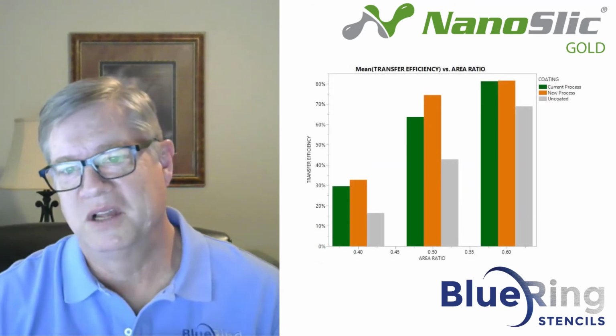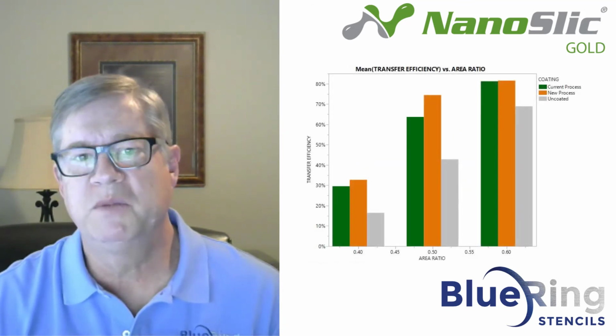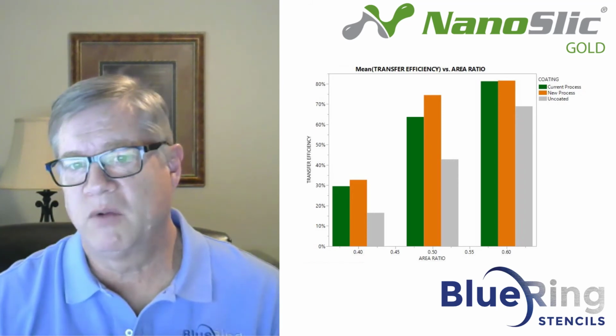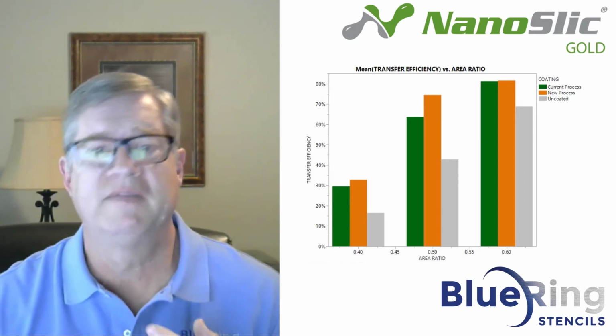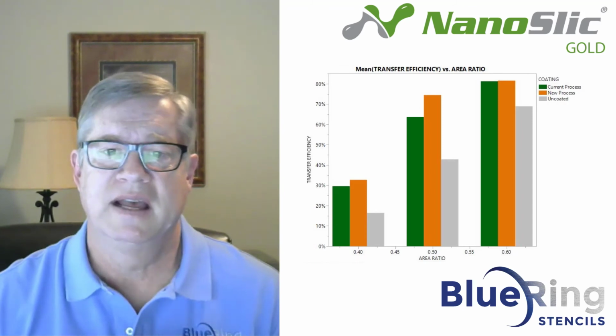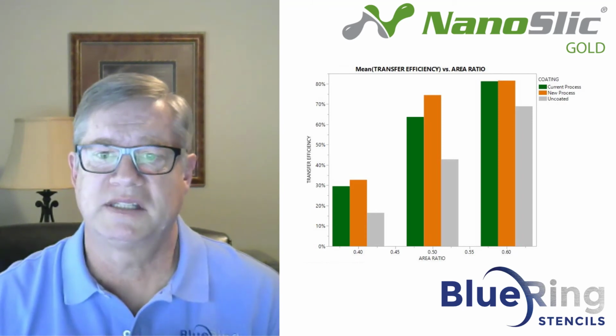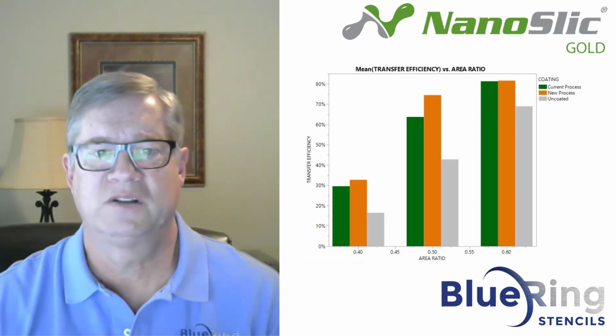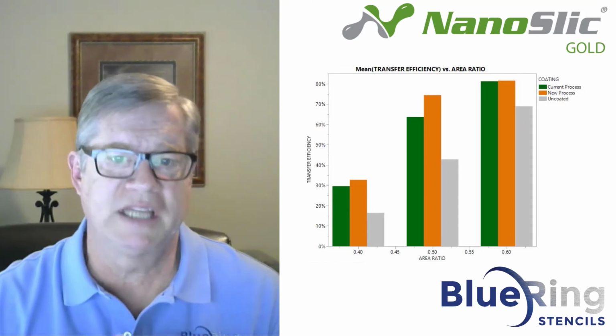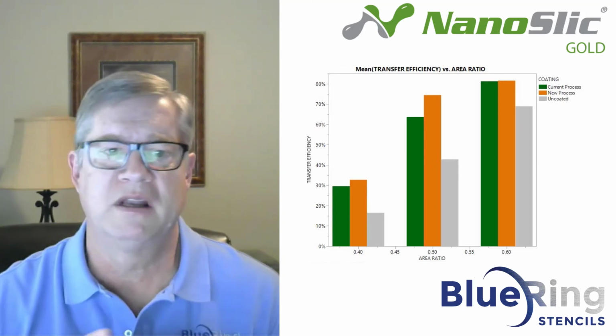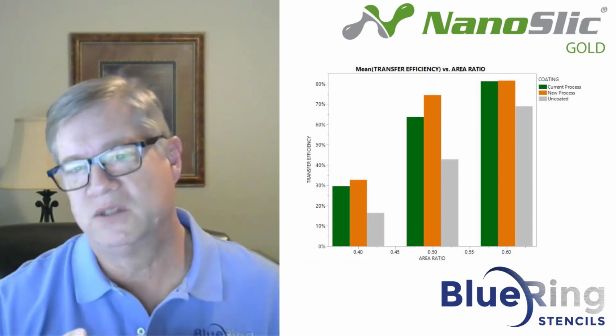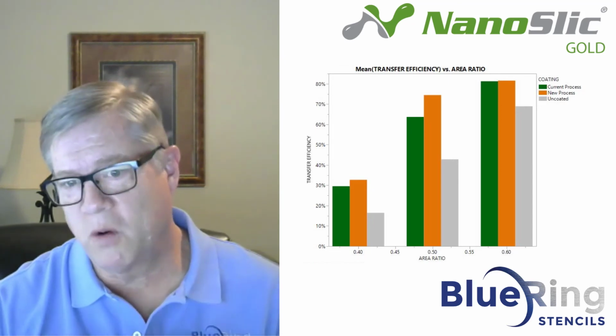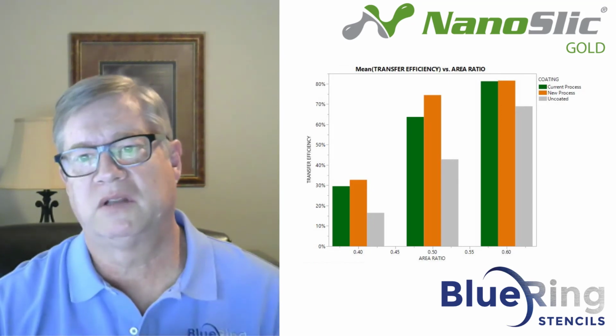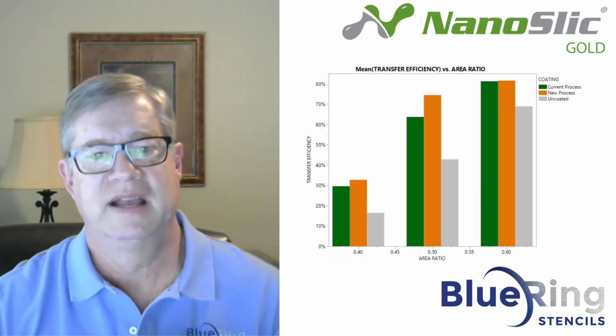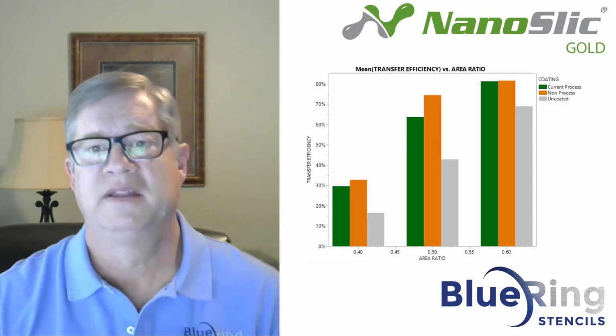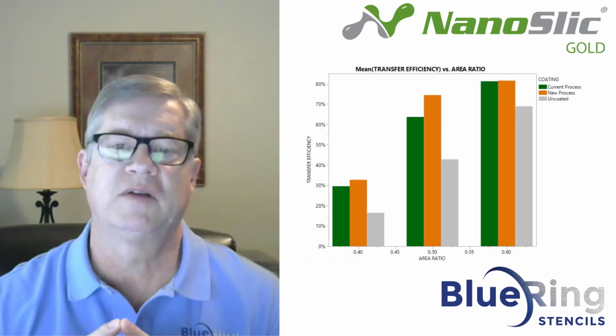In this chart, we're looking at square apertures with a 2mm corner radius, with area ratios of 0.4, 0.5, and 0.6. As you can see, both coating processes, current and the new modified surface coating, show significant transfer efficiency improvement over a non-coated stencil. As is normally seen, area ratio apertures lower than 0.6 typically show the largest gain in solder paste release, and as the area ratio increases, the improvement in transfer efficiency decreases.